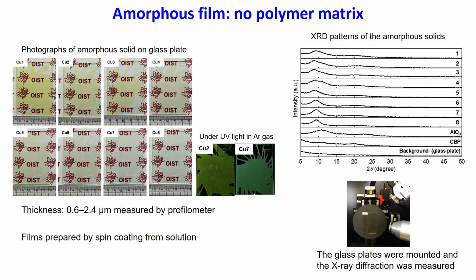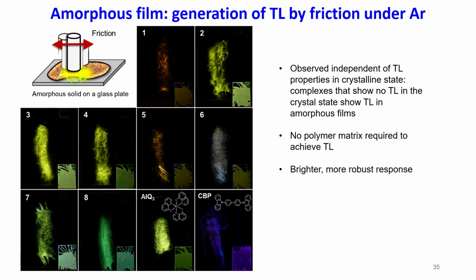So what about the amorphous state? How do we make it? With the help of a postdoc in our group, Daniel, we made amorphous films by spin coating containing these copper complexes, for example, simply on a glass slide. And they are amorphous. We can see it from film XRD. And surprisingly, essentially all of the complexes we've tried were mechanoluminescent in the amorphous phase.